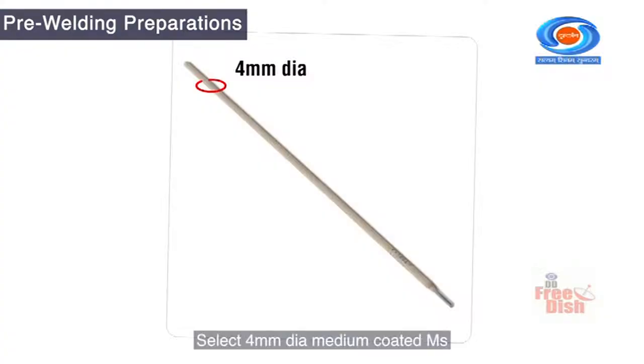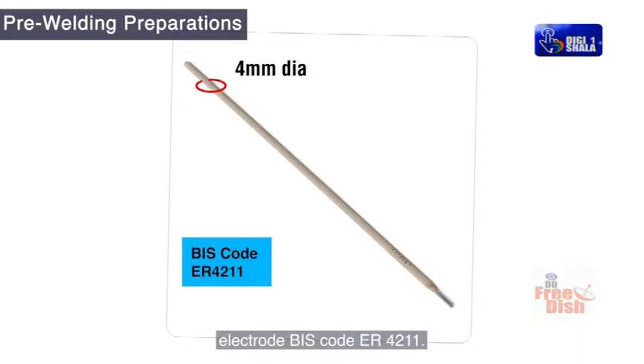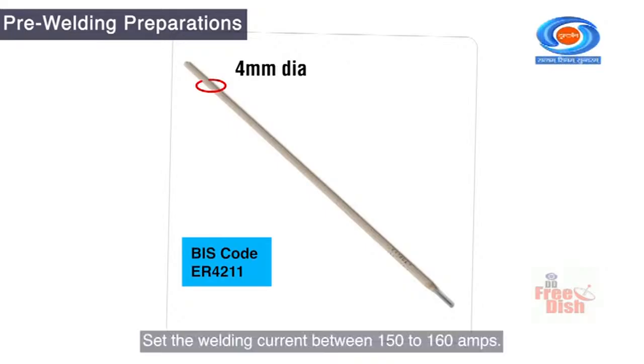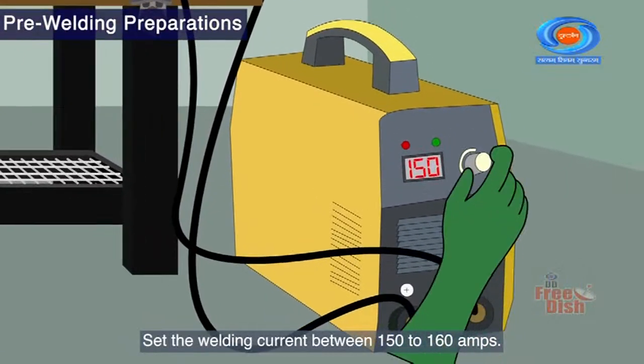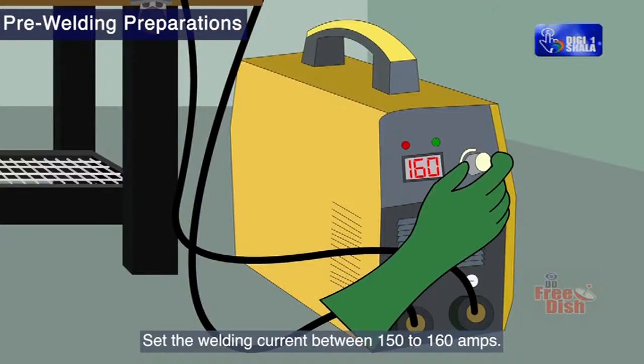Select a 4 mm diameter medium coated MS electrode, BIS code ER4211. Set the welding current between 150 to 160 amps.